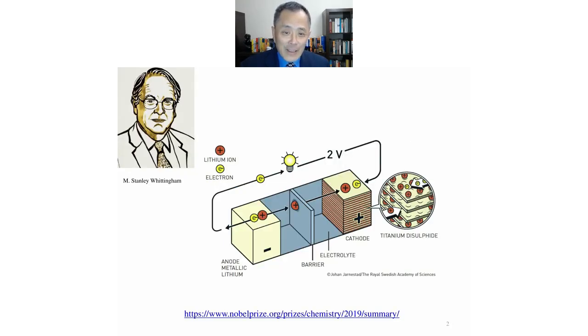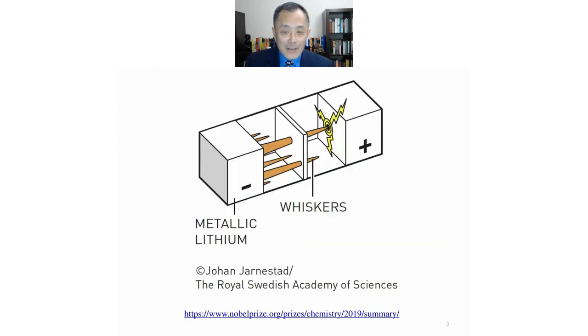As we all know, the 2019 Nobel Prize in Chemistry was awarded to 3 pioneers in the lithium-ion battery technology. Professor Stan Whittingham, then working in Exxon Research Center in the 1970s, developed a rechargeable lithium-ion battery using titanium disulfide as the positive electrode and metallic lithium as the negative electrode. This battery can produce about 2 volts. However, the metallic lithium has the propensity of forming whiskers or dendrites that can penetrate the separator and cause internal short circuit. And that'll be a safety problem.